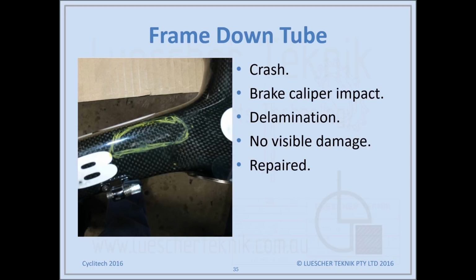We have another frame down tube, and this was involved in a crash. It's the down tube near the head tube junction, and the brake caliper impacted the frame as the fork turned around. So there was delamination. There was basically no surface indication, just a very light little scuff on the surface clear coat. But as you can see, the delamination is quite large. In this case, it was repaired and the bike was put back into service without issue.